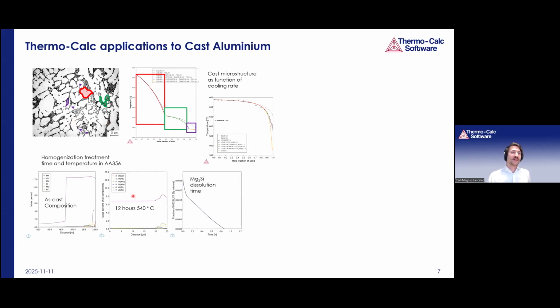And then we can bring this information into a diffusion simulation to simulate the homogenization of this cast structure. So we can simulate the flattening of these segregation profiles. Here is an example for 12 hours at 540 degrees Celsius. And also, maybe more important for these alloys, the dissolution time for different detrimental intermetallic compounds, such as Mg2Si phase.